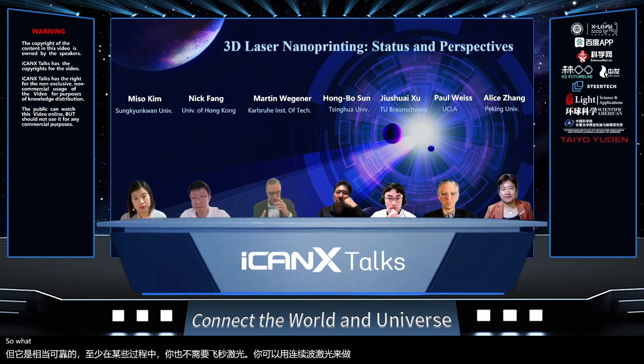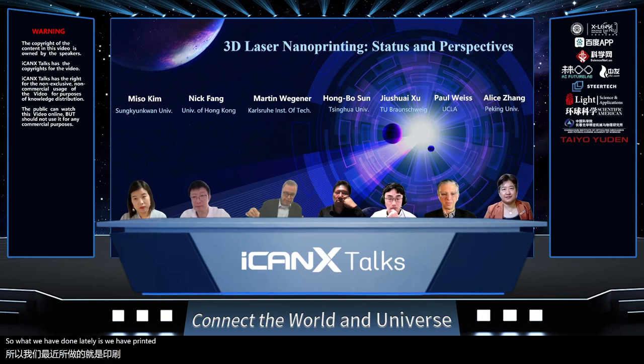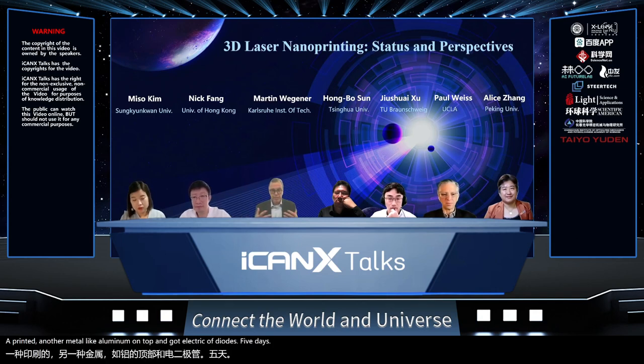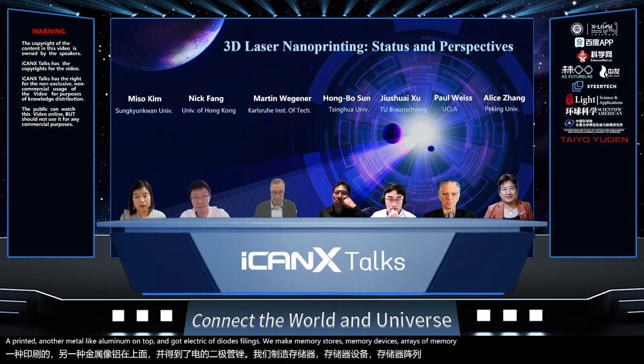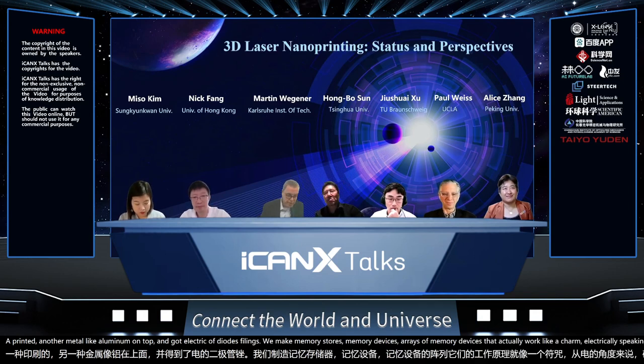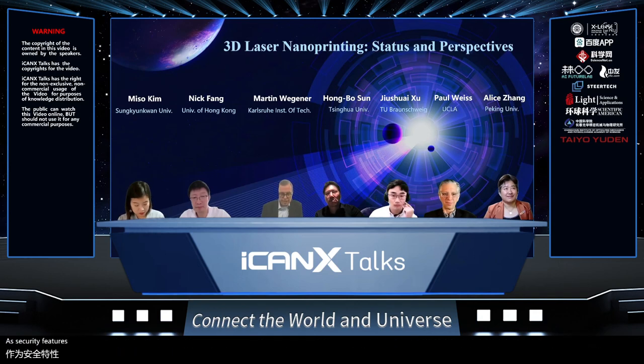So what we have done lately is we have printed metals like platinum, put zinc oxide on top, printed another metal like aluminum on top, and got electrical diodes by this. We made memristors, memory devices, arrays of memory devices that actually work like a charm, electrically speaking. And there are applications for these kind of things. You can use them as security features, as unclonable functions, as the community calls it. So this may actually be a no-nonsense application for printing electronics.